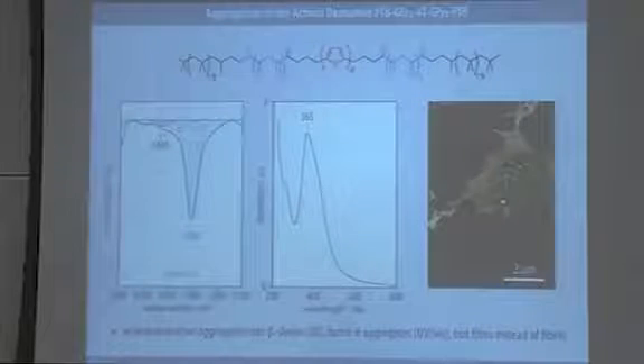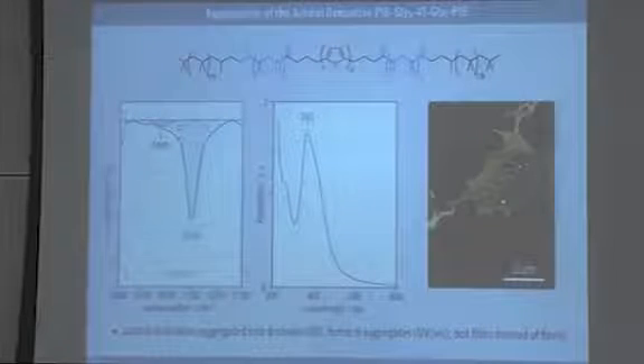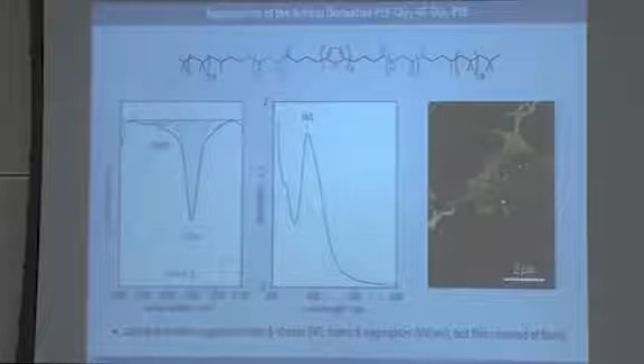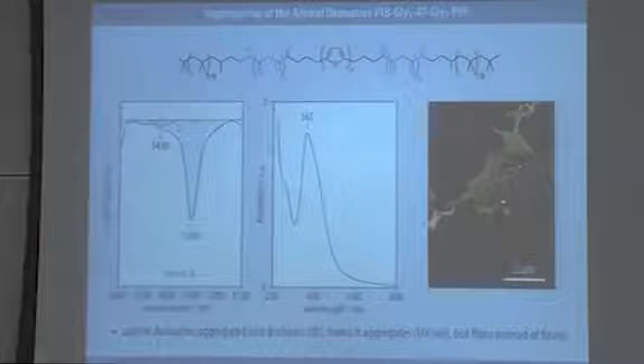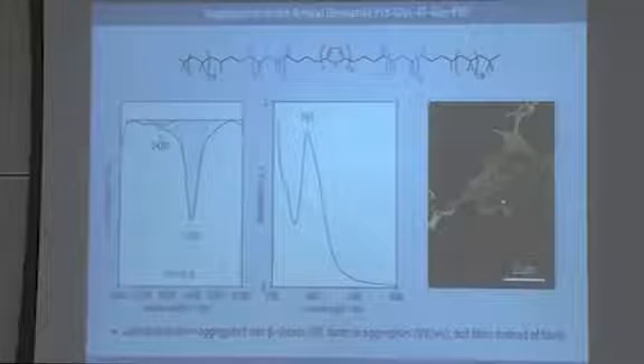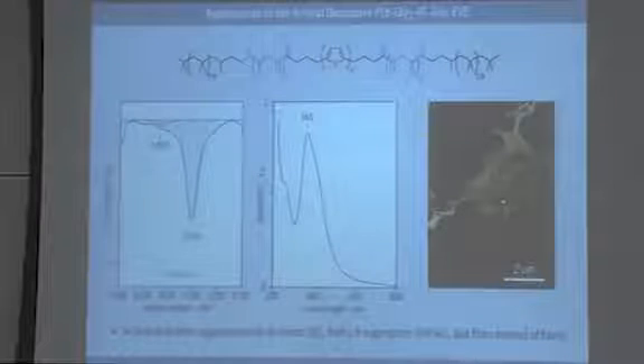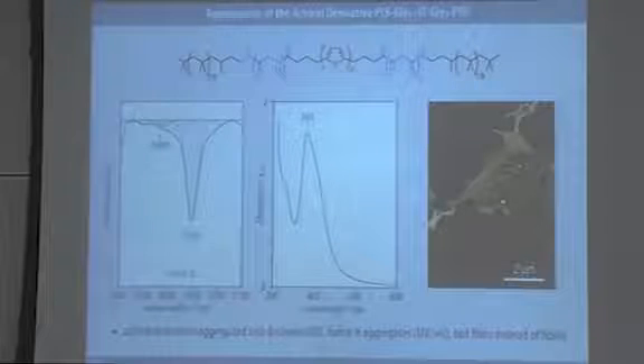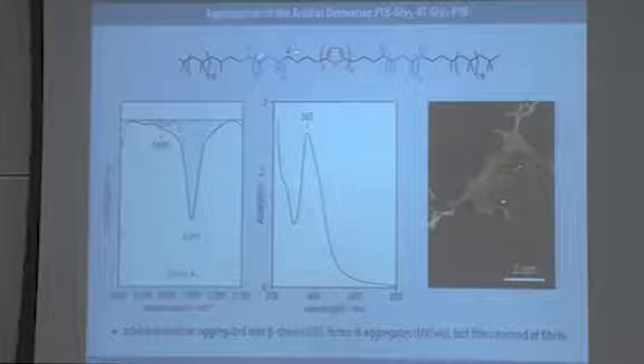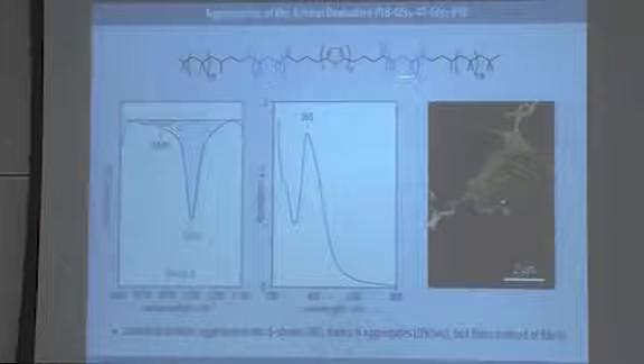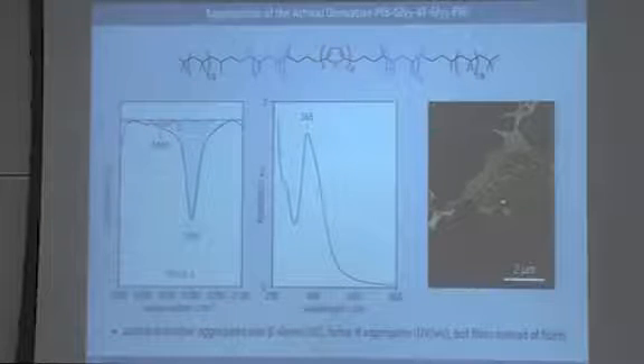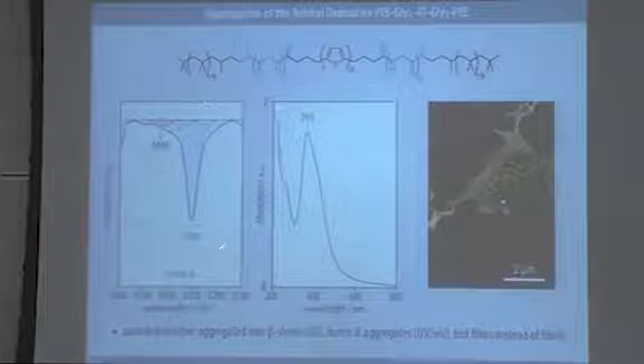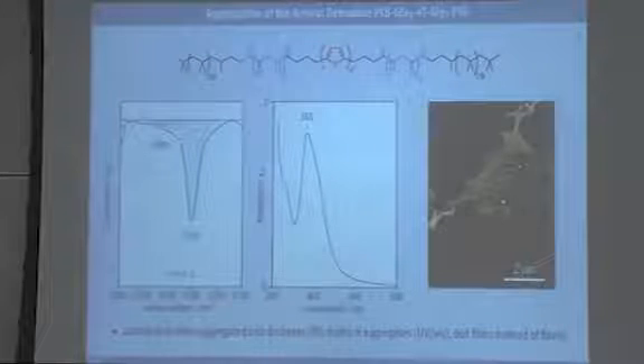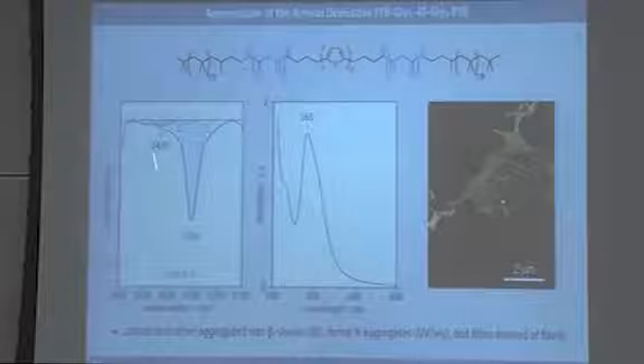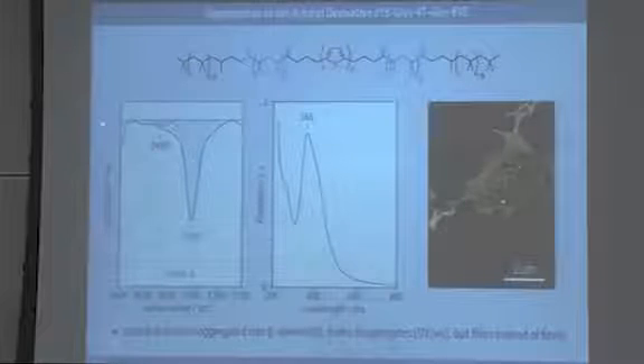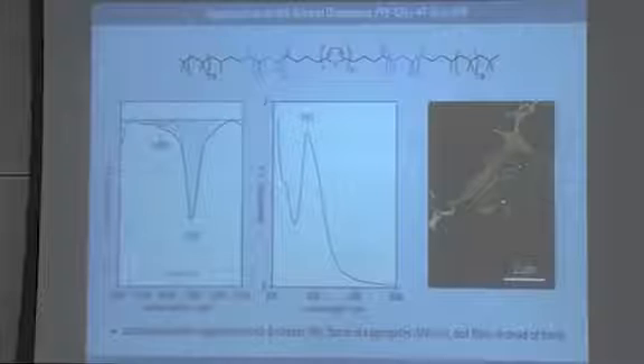So far everything is nice, and I would even say remarkable, and we understand many things pretty well, but we don't understand one detail that I would like to expose you to. And this is, if you go to the molecule that is achiral, where we replace the alanines that we typically use with simple glycines, the IR spectra shows that the molecule more or less on a local scale assembles in a similar way. So we obtain a nice beta sheet-like band of a highly ordered aggregate.